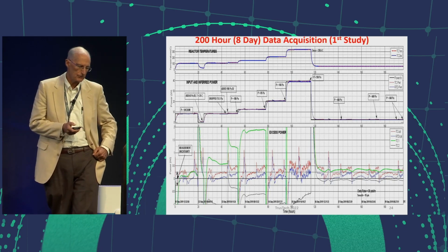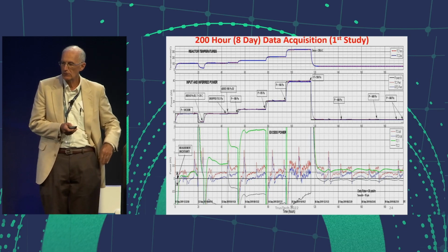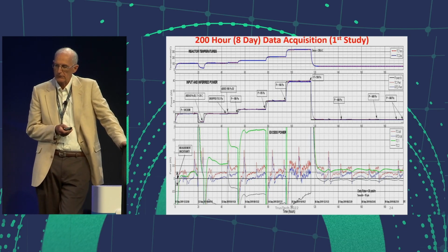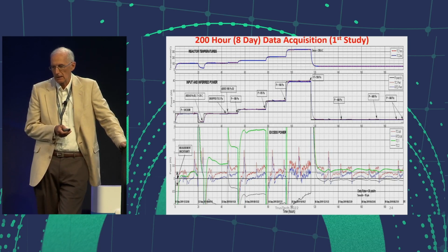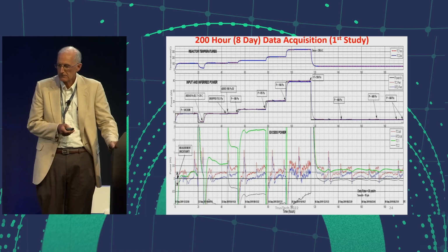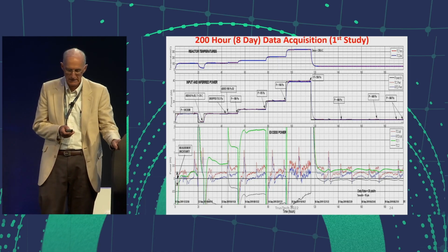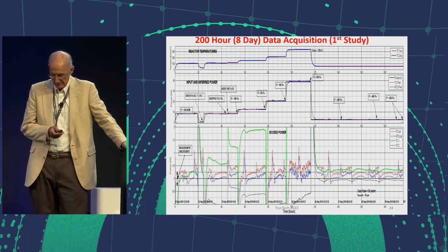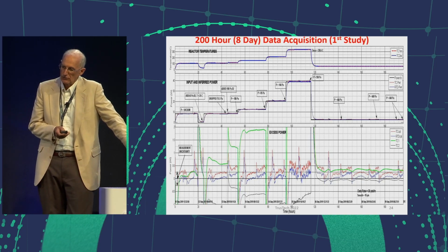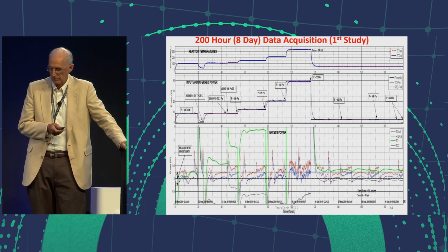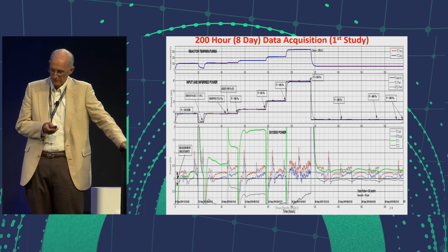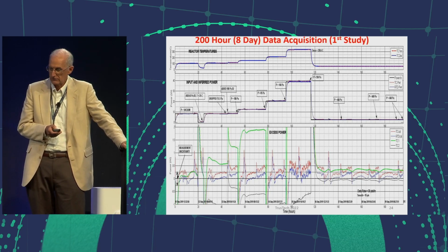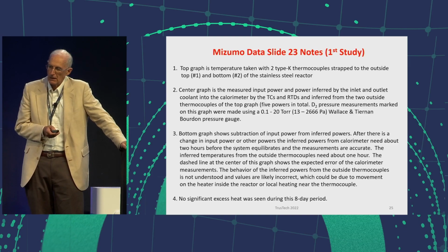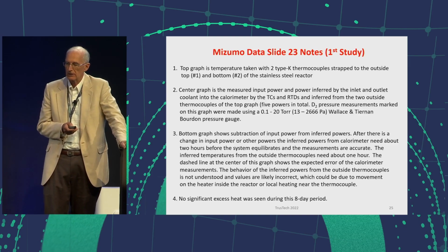So the first run that I did was 200 hours, and the first part of this data was treating the material, and then also treating it with hydrogen. At the time, I did not have a pressure gauge for the readout on it, so all along this data is the pressures of the hydrogen that was used. The short story on this is that no excess heat was discovered. This slide discusses the previous data slide in detail.